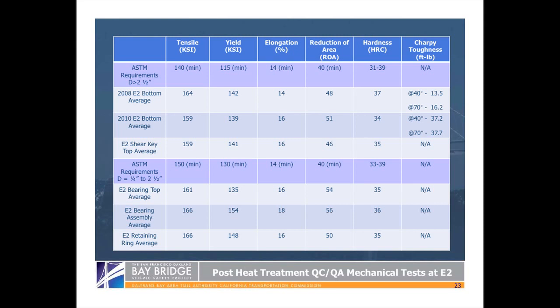If you move over to the right and you look at the hardness characteristic of those bolts, you'll see a difference. In other words, the 2008s are quite a bit harder than the 2010s on average. What you will see above that is the ASTM standard, which has a range there of 31 to 39. So the higher up you are on the range, the harder you are.